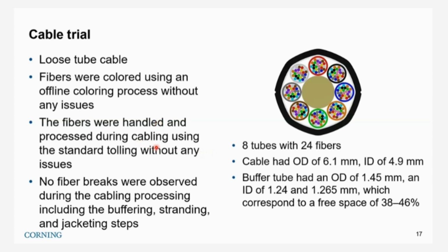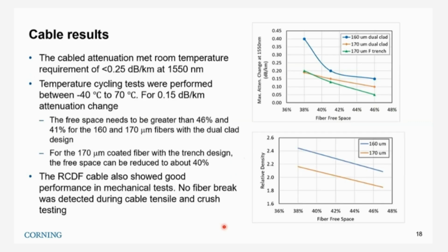In the cable trial, we handled the fiber using the standard tool. We did not have any issues handling the reduced coating diameter fiber. Also, we did not see any fiber breaks during the cable processing and the subsequent cable testing. Now let me show you the cable result.